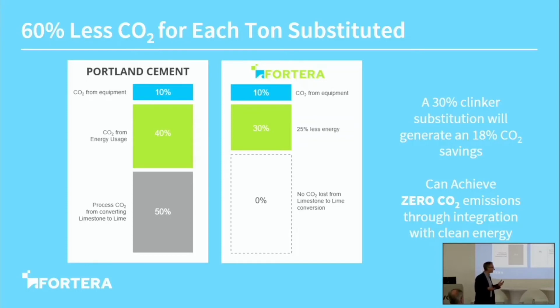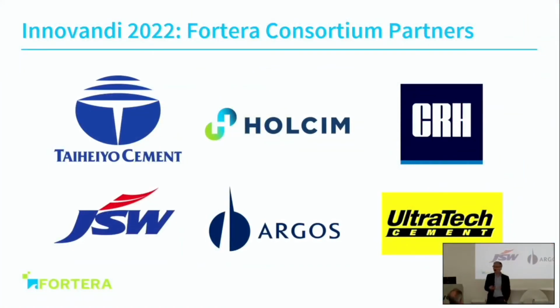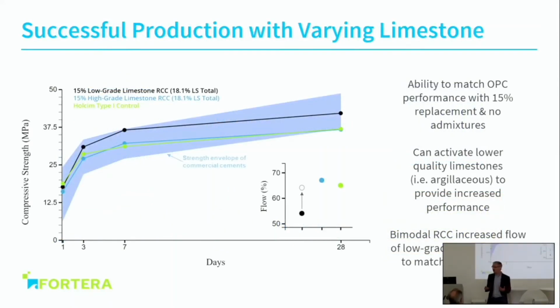This powder can be used either in blends with Portland cement and other cementitious materials. And it's how we would save CO2 if we replace some clinker by our product. This is what we have tested in the frame of the Innovandi Open Challenge. It can also be used pure as a binder, and I will say a word later on the topic. We have been very happy to have a big consortium with major players. Thanks to Taiheiyo, Holcim, CRH, UltraTech, Argos and JSW, and it was really a pleasure to work with a consortium and to do some tests of blends between our reactive calcium carbonate and Portland cement.